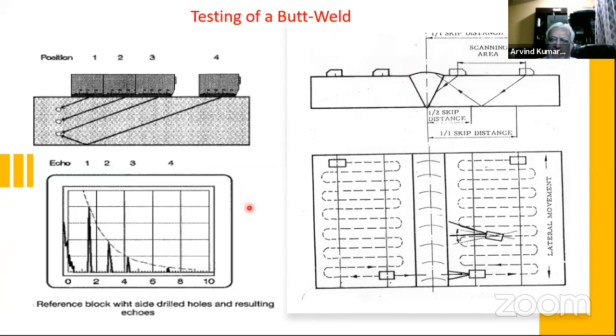Now, what are the other things to be looked into? Once I have plotted this DAC, I note down the amplitude shown on my UT machine. Suppose it is 38 decibels. I note that as 38 decibels. Scanning has to always be done at 6 decibels more, that is, double sensitivity as we call it.